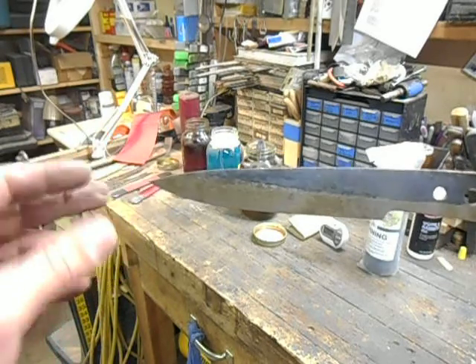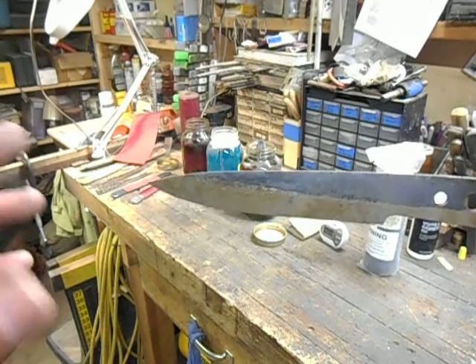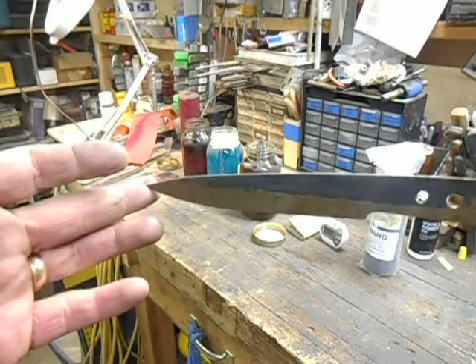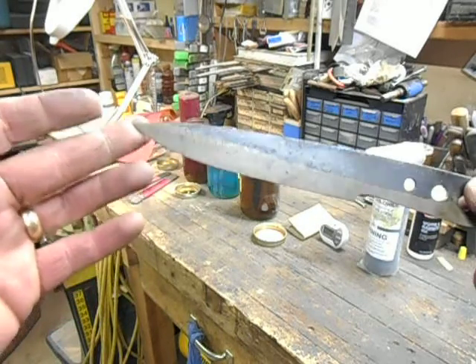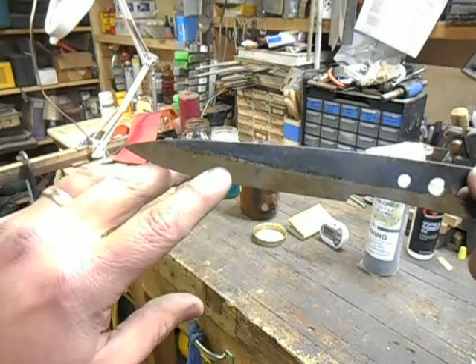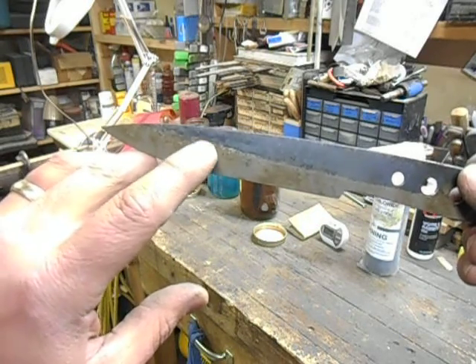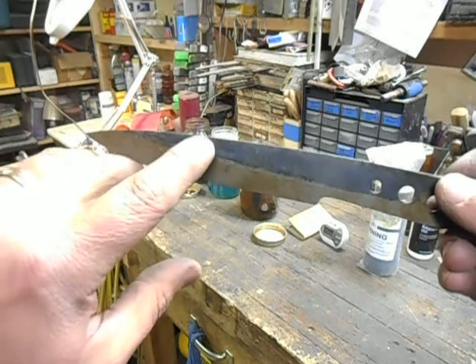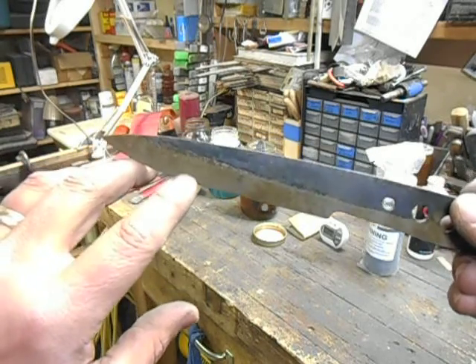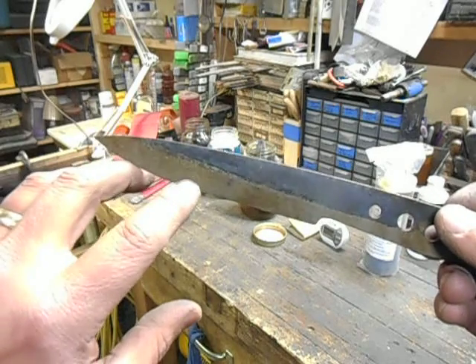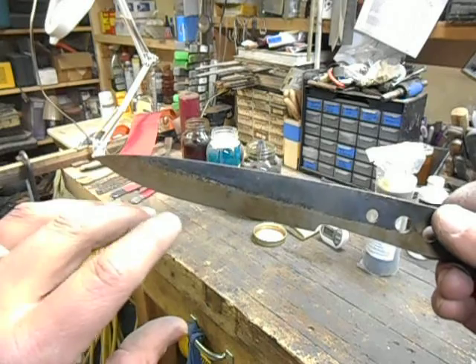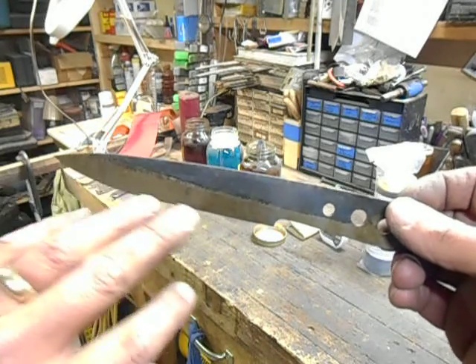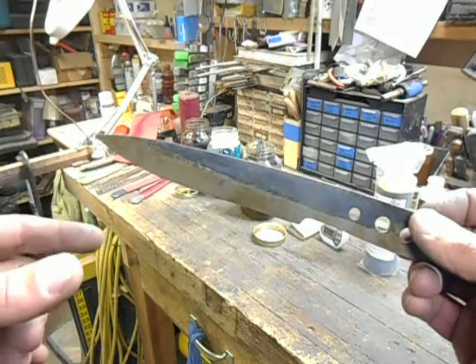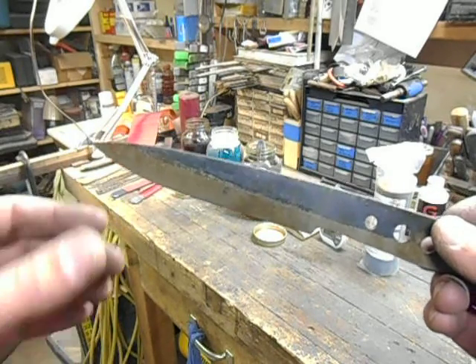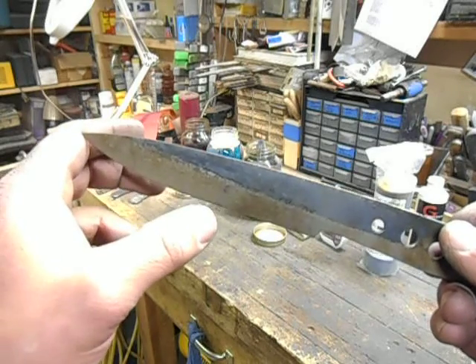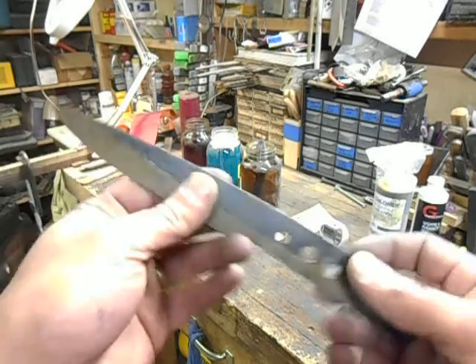Okay, now this one has been triple quenched in 130 to 140 degree canola oil. Alright, now you'll see the different colors in this blade right here. This is gray, a little bit of brown, and this is mostly black. Fresh out of the quench, this will be a solid gray. There'll be no brown. But then you wipe the blade off to get most of the oil off of it, and then when you stick it in your high-tech toaster tempering oven, the oil that's still on the blade will burn off and it'll turn this brown color.